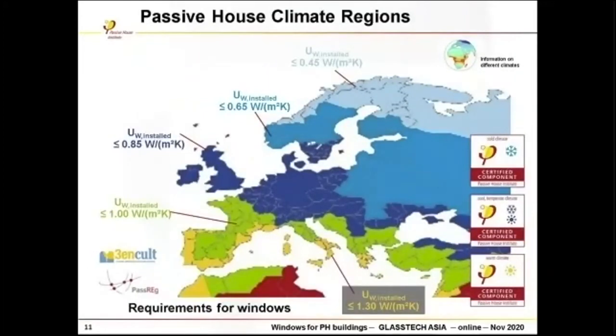From that, you see this map once more. You can see, depending on the temperature you have in wintertime, the overall window U value you should go for: 0.4 for the very cold, and 0.6 for maybe Sweden, 0.85 for Central Europe, and a little more relaxed for Spain and so on. In South Italy, you only need a 1.3 U value. This is now the goal, to see what quality we should require and where to go.